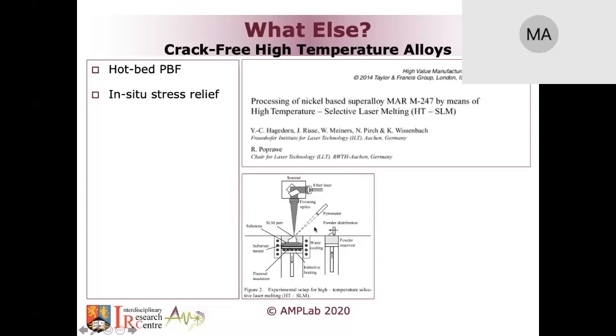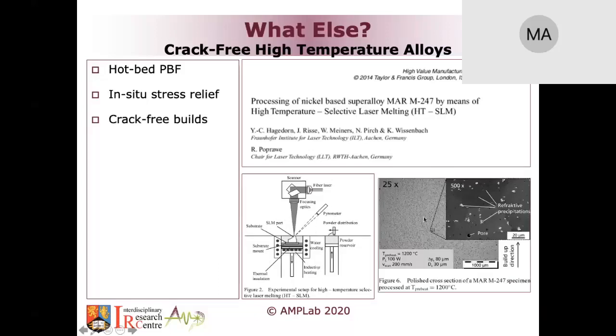They tested that on a nickel-based superalloy called MAR-M 247, which is the alloy that everybody is trying to make by additive manufacturing. And for the first time ever, in 2014, they were able to create a crack-free nickel-based superalloy when they used a bed temperature of 1200 degrees Celsius. 1200 is very, very high. So they did create a crack-free build.